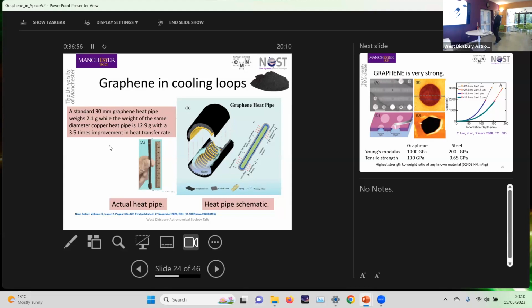Turns out that if you make these heat pipes with graphene, you can make them about 3.5 times more efficient and a lot lighter. So a 90mm graphene heat pipe would weigh 2.1 grams, whereas its copper equivalent is 12.9 grams. So again, getting it into space, there's just no comparison. So a lot of work is being done. This particular one's made from a graphene polymer composite material as the pipe, and then carbon fiber is being used as the wick in this instance. It was found to be more efficient than a graphene version.